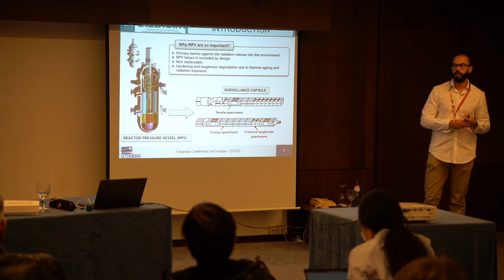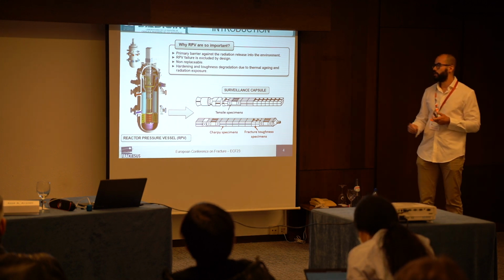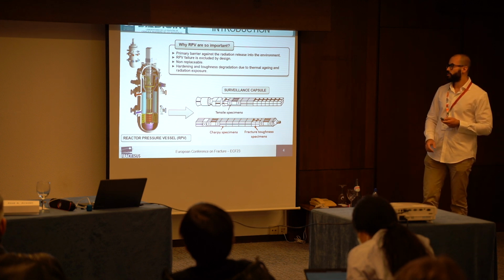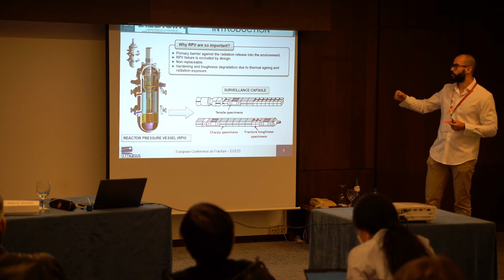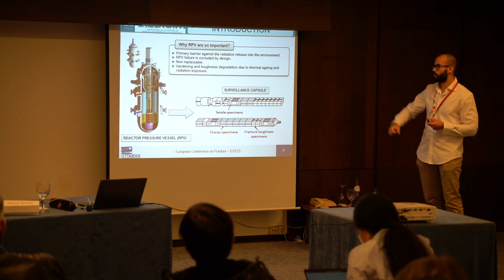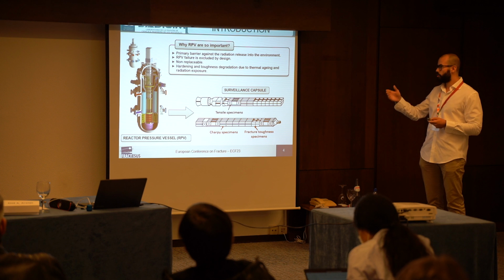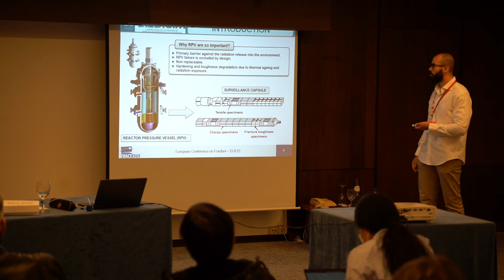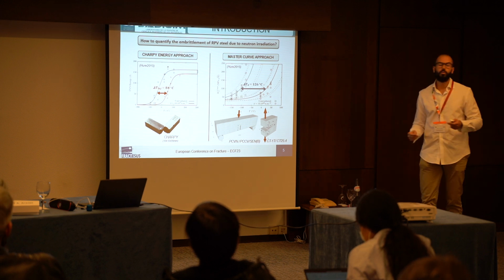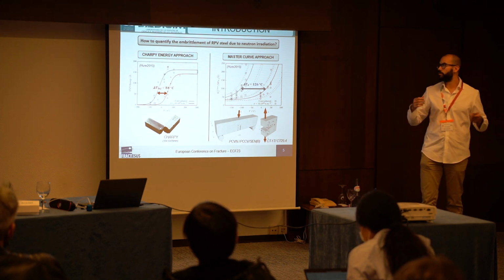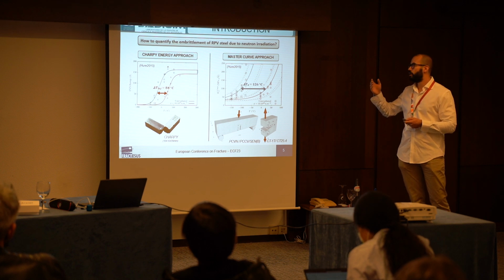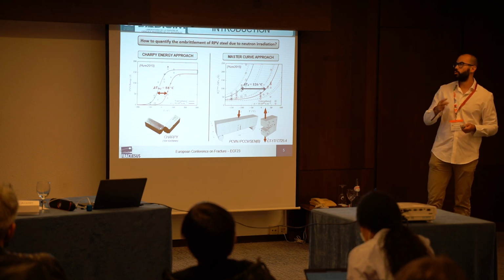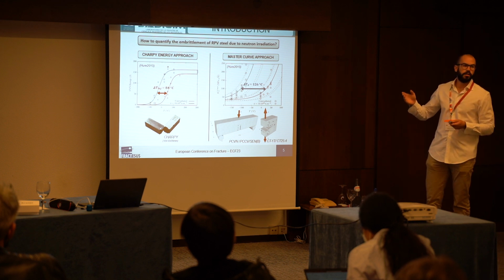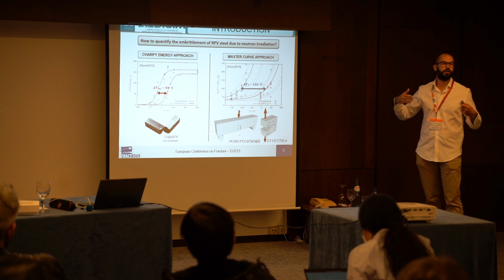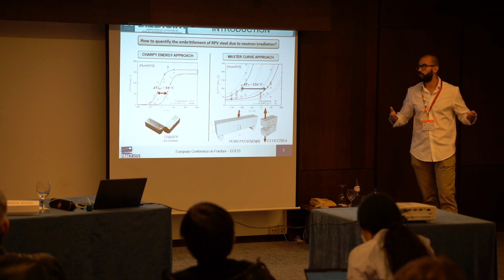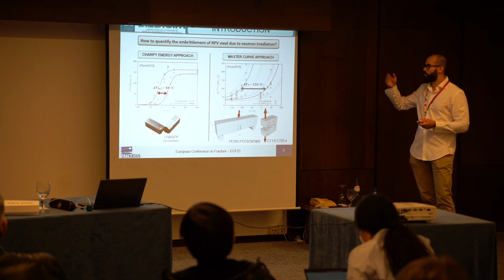In this sense, the nuclear power plants have implemented a surveillance program, which consists of removing some specimens from the surveillance capsules that, of course, are inside the RPV, to be tested from time to time. So, once the results of these tests are obtained, the embrittlement of the RPV can be measured by mainly two approaches. The first one is based on Charpy techniques, that is the most common, mainly for historical reasons. And the second one is the master curve approach.